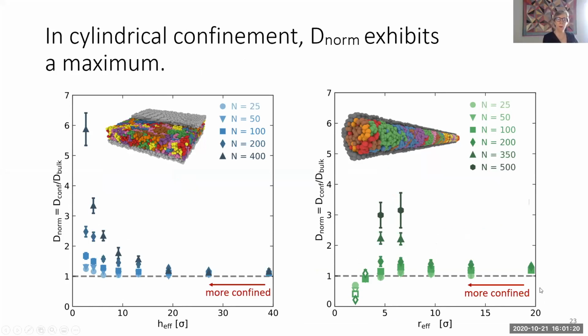So as we go to a more confined system, we do see the diffusion coefficient increase, and then it decreases. So we have this non-monotonic dependence on confinement, whereas in the thin films, it just gets faster and faster and faster as the polymer disentangles. Here we know the disentanglement is happening. The disentanglement is actually even more sensitive to confinement than it is in the thin films. But so we see this upturn, it's more dramatic for higher molecular weights, and then it gets easier. First it gets faster to diffuse, and then it gets slower to diffuse. And this we understand